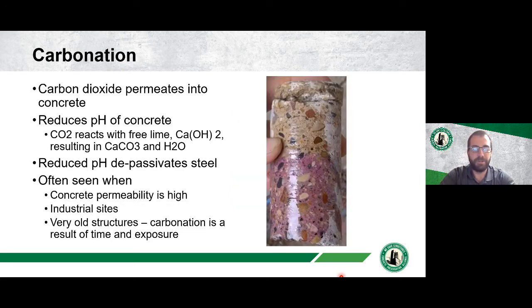Another source of corrosion is carbon dioxide, carbonation of the concrete. Concrete will absorb carbon dioxide from the air, and as it does, that carbon dioxide will react with the free lime and lower the pH of the concrete. Here we have a concrete core with a pH indicator solution sprayed on it. You can see the pink area is where the pH is high, and the clear area is where the pH is low. So that carbonation front has reached this boundary here.